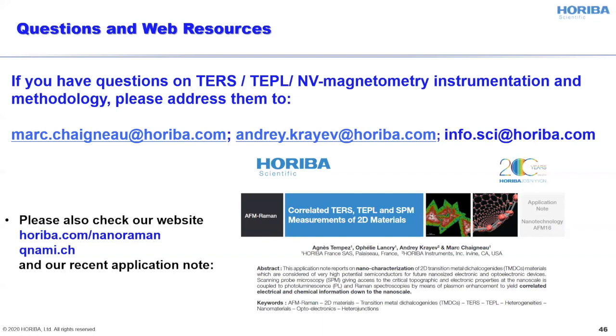And in terms of measuring the density of states in these experiments, I think that if we have a sufficient number of excitation lasers, and we have proven that our probes can work, from gold-based probes, can work from 594 nanometers and all the way up to 830 nanometer excitation, and silver-based probes can work starting from green, just analyzing how the Raman spectra or TERS spectra change as a function of excitation wavelength, I think that we can have very interesting and quite unique information about the properties of the materials.